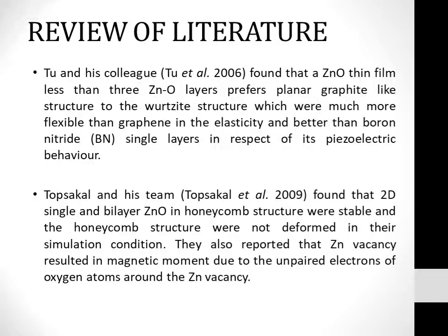Now let me highlight some of the work that has been published in this field. Back in 2006, Tu and his colleagues found that some ZnO thin films prefer a graphite-like structure, a monolayer structure, rather than the wurtzite structure, which were much more flexible than graphene in elasticity and better than boron nitride single layers in respect of piezoelectric behavior.